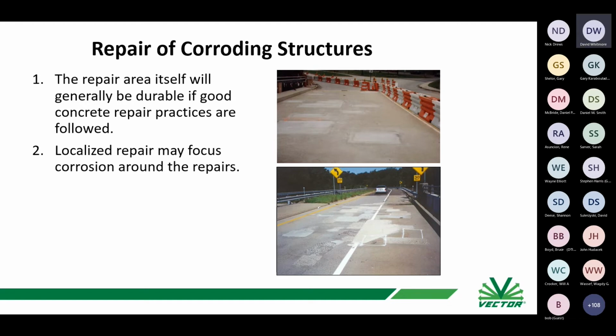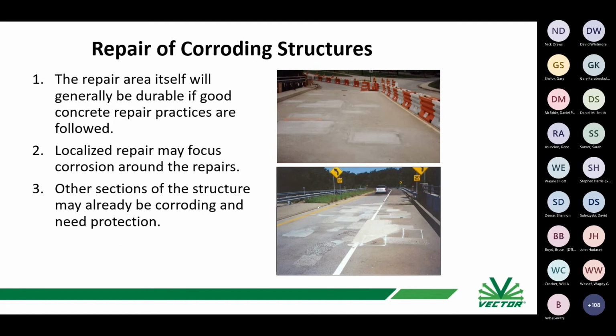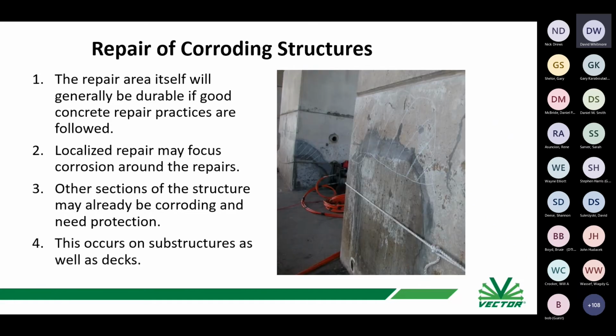That's a bridge deck from Connecticut. This happens to have about 4 or 5 different generations of patch repairs on the same bridge deck, and some other new ones that are marked out for repair. But if we want to deal with this problem holistically, which Arnie kind of mentioned earlier on, we need to think about other sections of the structure that are between the repairs. We have stuff that's directly adjacent to the repair, which might be impacted by the repair. And then we have the stuff that's maybe several feet away from the repair, but it's chloride contaminated over there and it may be corroding on its own. And we need to think about that. And these pictures I've shown you in my graphic are all showing a simplified bridge deck, but the exact same thing happens on bridge substructures.